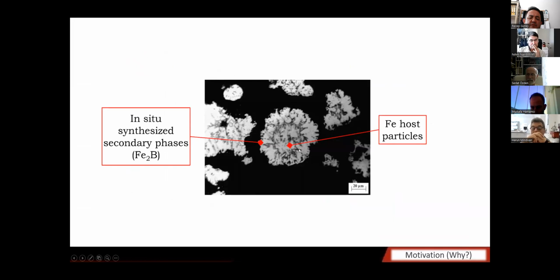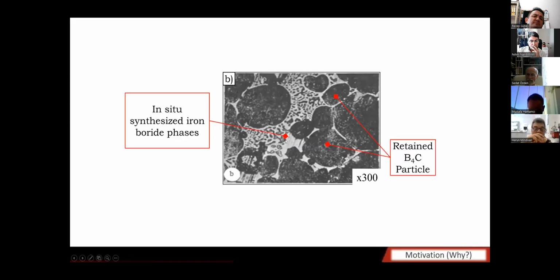Here is another example. This is a Turkish researcher who used a similar approach, not exactly similar, but he individually borided these iron host particles, and he managed to get these ceramic phases on the surface of the iron particles. Here is another example in which in situ synthesized iron boride phases are used, but because they used a very high temperature, a liquid phase was formed on the surface, so they were not able to control the composition of these phases. But this is also an example from the literature in which the iron particles have been borided.